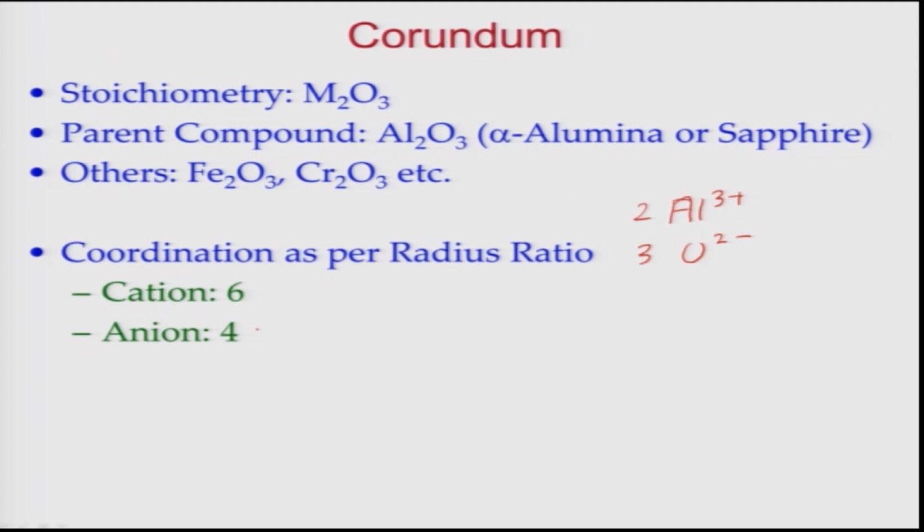And as you can see, since you have only hexagonal close packed cell which has 3 oxygen atoms per molecular unit. So, hexagonal close packed cell has only 1 octahedral interstice per atom, which means only 2/3 filling of interstices is going to happen. So, only 2/3 of the octahedral voids are filled in this structure.